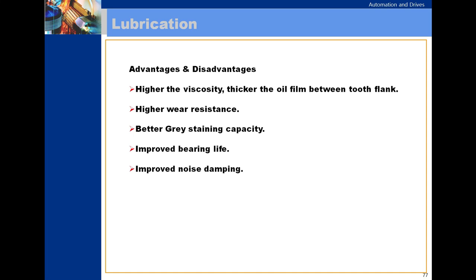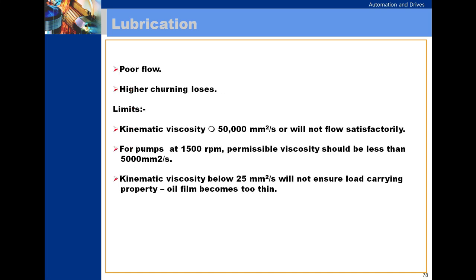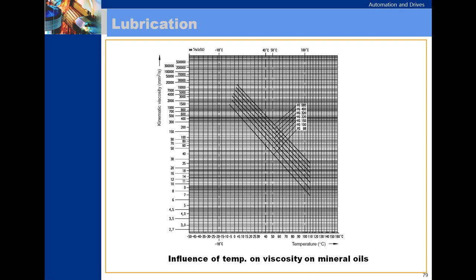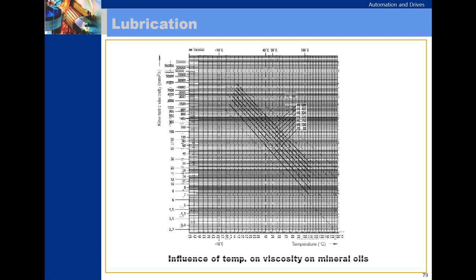Advantages and disadvantages of lubrication: the higher the viscosity, the thicker the oil film between the two flanks, higher wear resistance, better grey staining capacity, improved bearing life, improved noise damping. But poor flow and higher churning losses. Limits: kinematic viscosity above 50,000 square millimeters per second will not flow satisfactorily. For pumps at 1500 rpm, permissible viscosity should be less than 5000 square millimeters per second. Kinematic viscosity below 25 square millimeters per second will not ensure load carrying property; the oil film becomes too thin. The influence of temperature on viscosity on mineral oils.